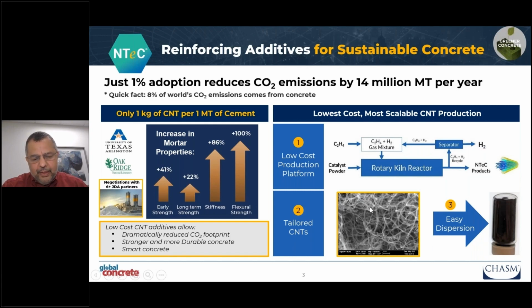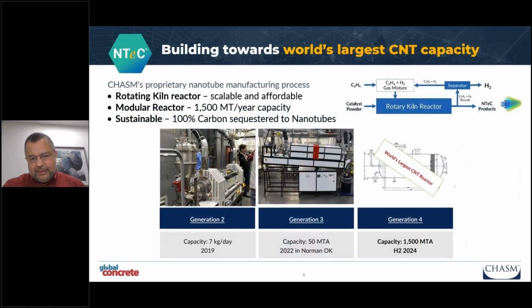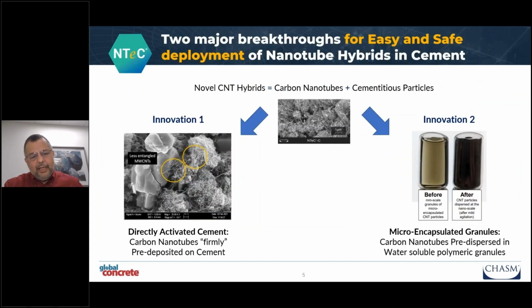And dispersion, universities have been using liquid as a form of intermediate dispersion, and we realized this is not going to work. So we pivoted into two forms of dispersion. One is a solid dispersion where you directly deposit the nanotube on the cement, and this is what we are going further with. The second one, which we're also working on, is a microencapsulated granule where you encapsulate it in water-soluble systems. And these two forms of dispersions have made it possible for us to cross the dispersion barrier.